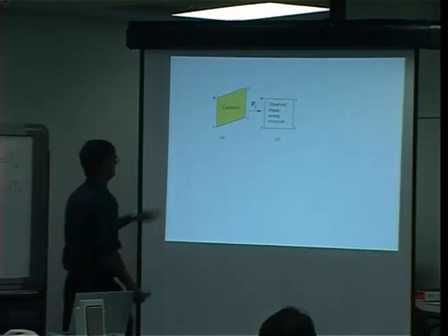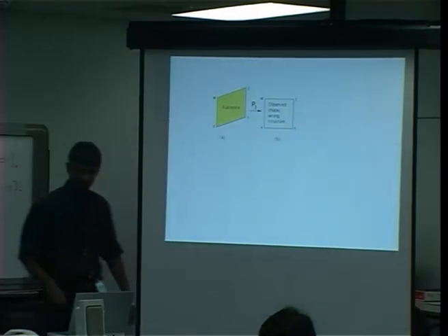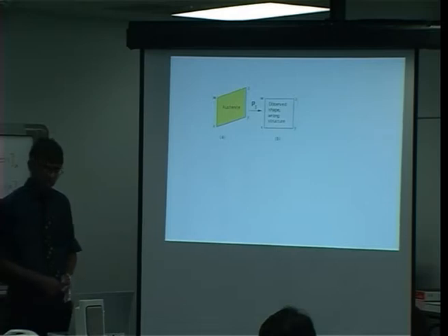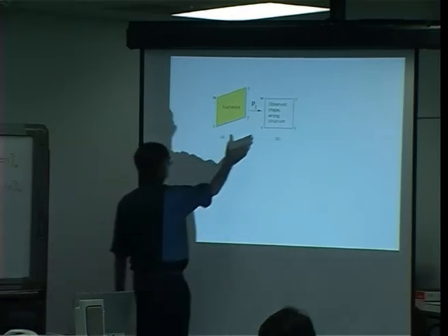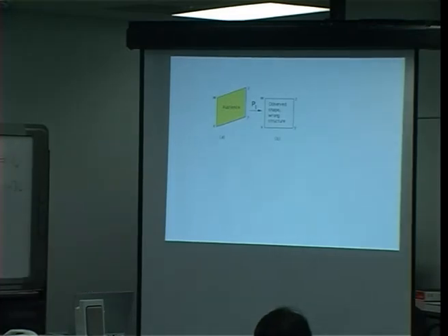And we'll call this shape deformation the matrix P1. In order to produce the right structure, the total deformation here must be an invariant line strain. Now, supposing I have an invariant plane strain on this plane and another invariant plane strain on this plane, what is that total deformation? So I'm operating two different shears. What is the net result?